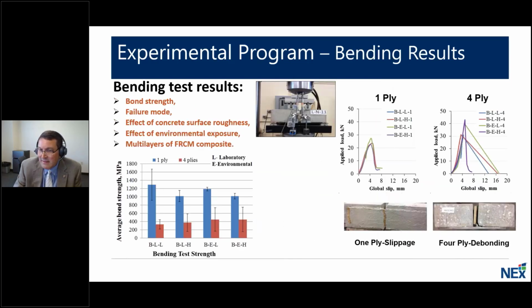Results from the beam bending test also indicated that a lighter ICRI roughness preparation was better than a rougher one in terms of bond, and it produced better bond behavior, similar to what we would see in an FRP system using epoxy. The environmental conditioning did not have a significant impact in the beam test.